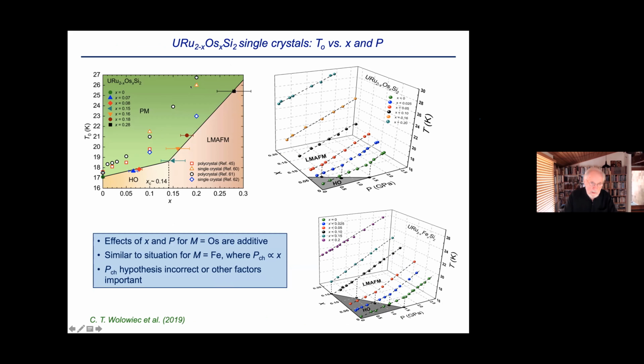And these are data on the polycrystalline samples, and they differ from the data on the single crystal samples. These materials are harder to deal with, but these concentrations have been independently measured by EDX measurements. So we believe this is what the phase boundary actually looks like. So this is paramagnetic, hidden order, and then the large moment antiferromagnetic regime. And then if you do the same kind of high pressure measurements, you get data similar to what I showed you before. You can pick out the relevant temperatures and pressures.